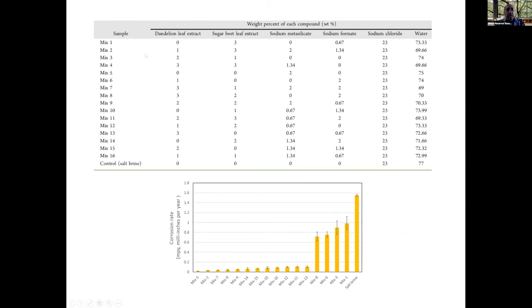In the next step, we use the uniform design to reduce the number of experiments that we want to do. And we use this dandelion leaf extract, sugar beet leaf extract, sodium metasilicate, sodium formate, and 23% sodium chloride. We dissolve this mixture in water and perform different experiments, such as measuring the corrosion rate of the steel coupon exposed to these deicers for 24 hours. You can see here all of the samples have a lower corrosion rate compared to salt brine, which is